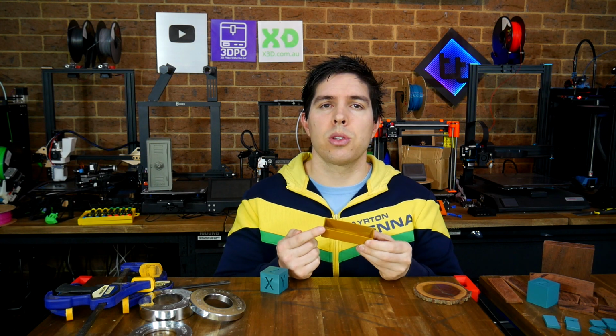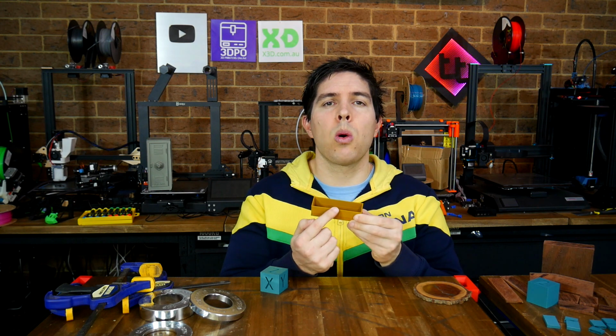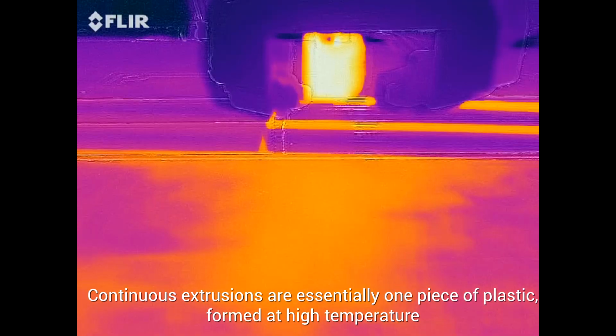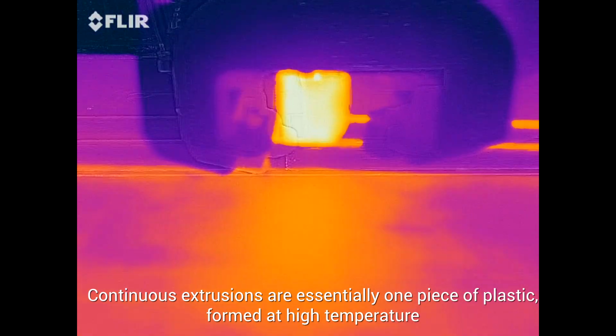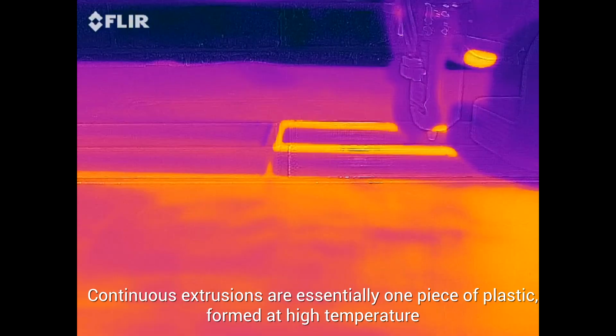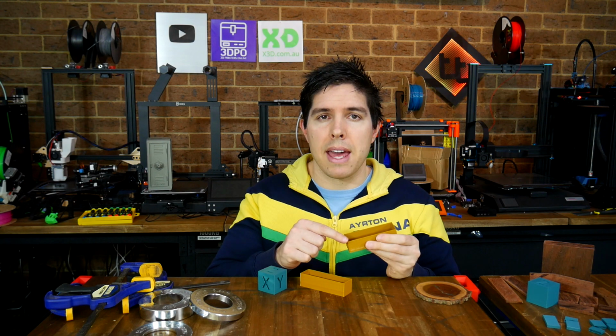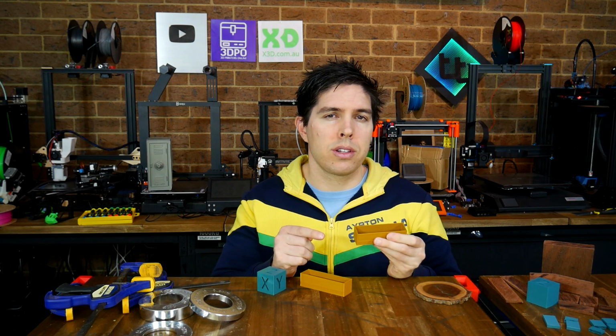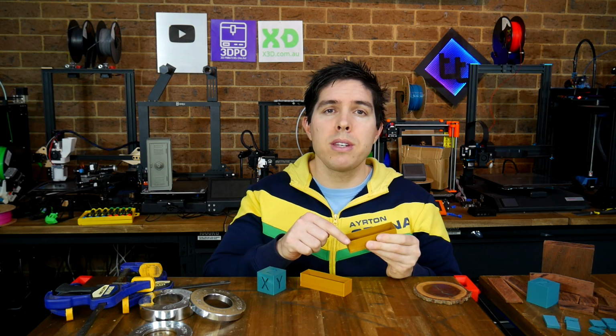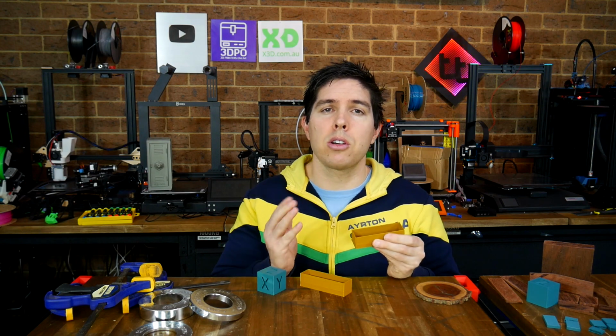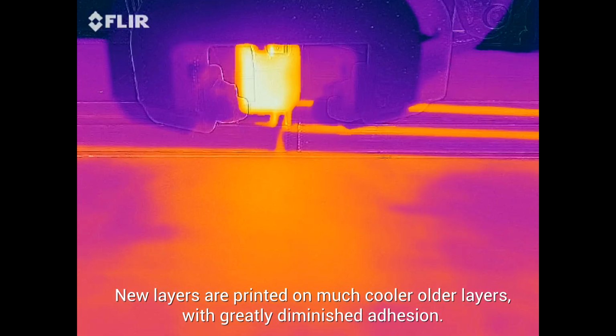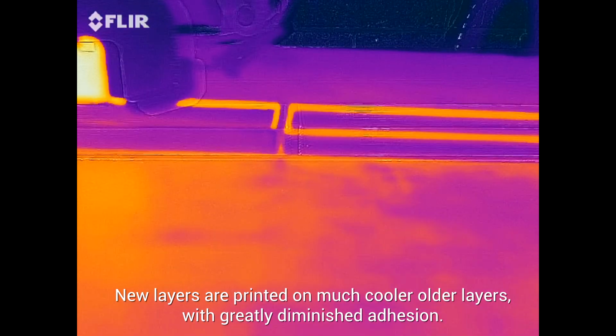In the footage you just saw, the continuous extrusions were all done at 220 degrees Celsius, and as such, each segment of the line is well bonded and very strong. Conversely, when we come back to add a new layer, we're still printing at 220 degrees Celsius, but we're bonding that to the previous layer, which is now cooled to ambient temperature. So the bond and therefore the strength is inferior.